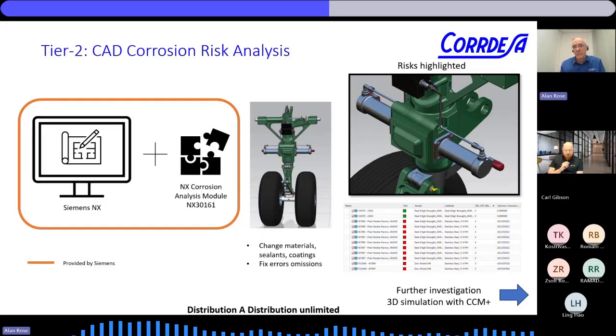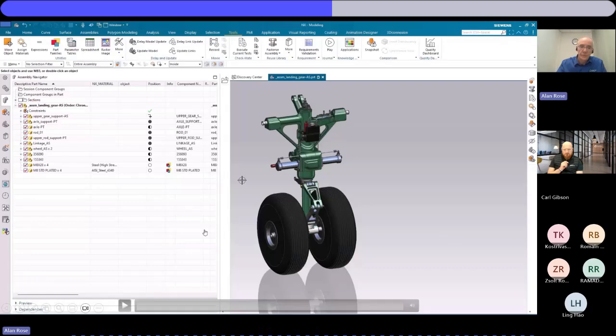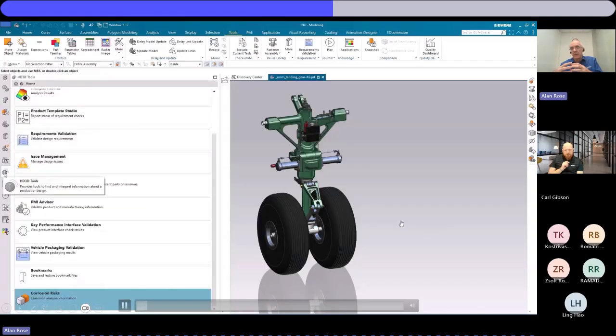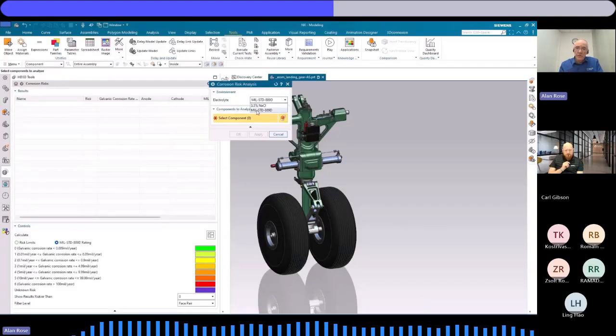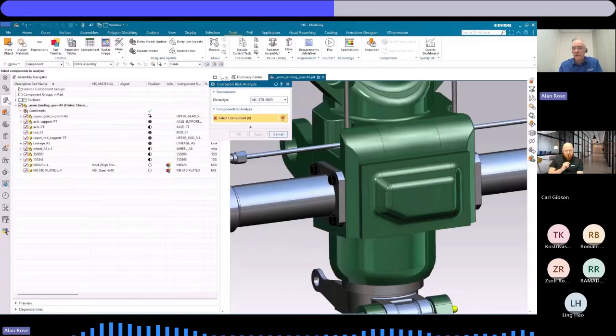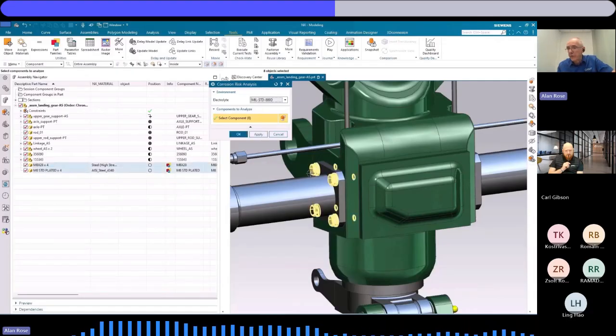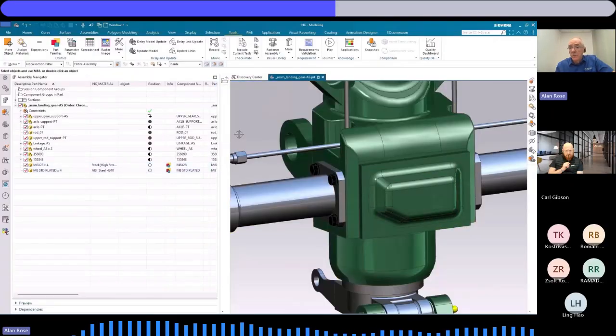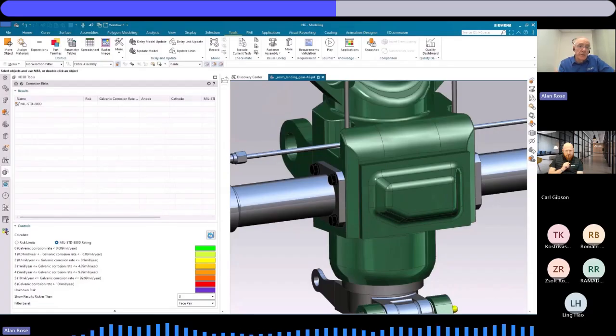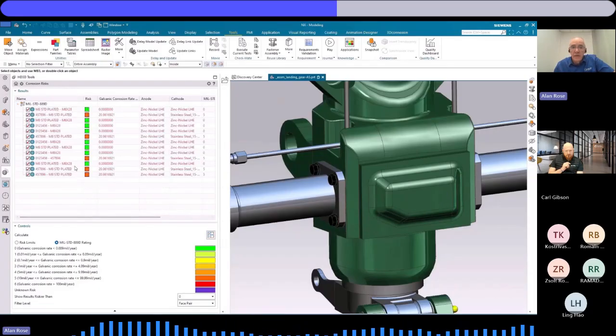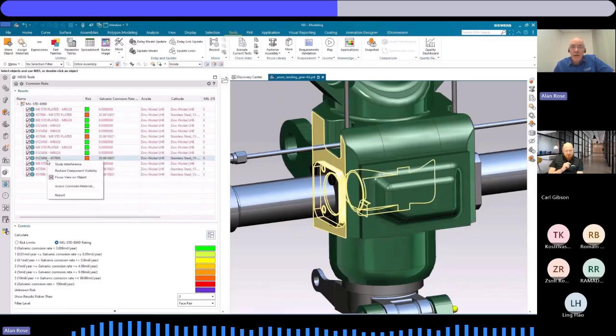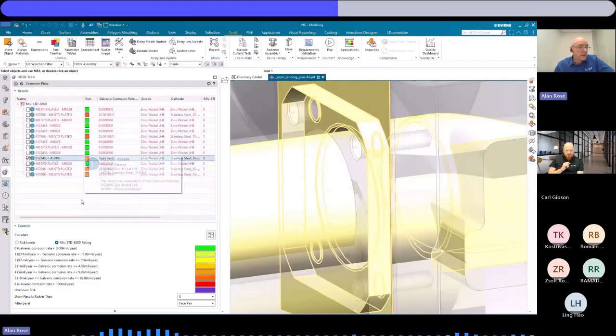But if you have a CAD system with your bill of materials with all the coatings already assigned, which can be done, then you can just, within that CAD system, press a button and it will give you a table down here and tell you what the corrosion rates are. So this is the way it can be deployed. Very early on in the design process, you can choose your environment again. You can just choose a few fasteners or a subsection of your geometry, or you could choose a whole geometry. And you just press calculate corrosion, and it's really automated that mixed potential theory, that application, and applied the MIL standard way of assessing corrosion rate.